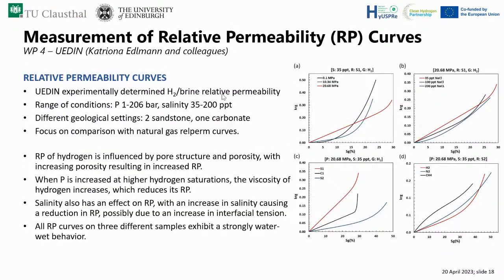Also in the report, and finally, the relative permeability curves work from Edinburgh. They experimentally determined the hydrogen-brine relative permeability for a range of conditions and compared that with natural gas relative permeability curves for 2 sandstones and 1 carbonate rock. And of course they found that the relative permeability for hydrogen is influenced by pore structure and porosity. Increased porosity results in increased relative permeability.